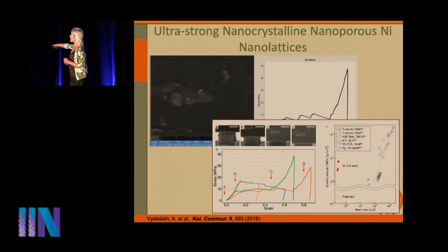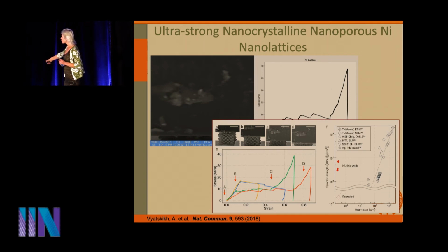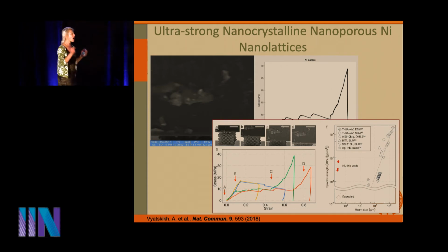But the additive manufacturing techniques that exist today seem to not deal so well with the size reduction. When their dimensions are about a millimeter, so this is 1,000 microns, right? So a millimeter, they're doing great. Their specific strength is very high. This is silver and titanium and nickel, nitinol actually, in fact. But as soon as you start reducing the dimensions from 1 millimeter even down to 100 microns, it loses strength very rapidly by 2 orders of magnitude. Additive manufacturing techniques that exist today are not robust against defects.